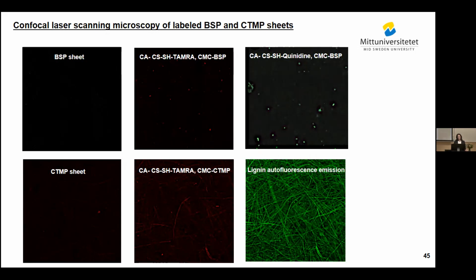so that it follows the lignin pattern. Here is the autofluorescence emission of lignin. But the starch that I labeled with the quinidine, I couldn't use for fluorescent labeling of CTMP because the quinidine has the same range of emission as lignin, but I could use it for labeling the bleached sulfite pulp. And it also shows that, yes, we have a heterogeneous distribution. It seems that the presence of lignin helped to have more polyelectrolyte on the surface, and also we have a better effect actually in CTMP compared with the BSP with this method.